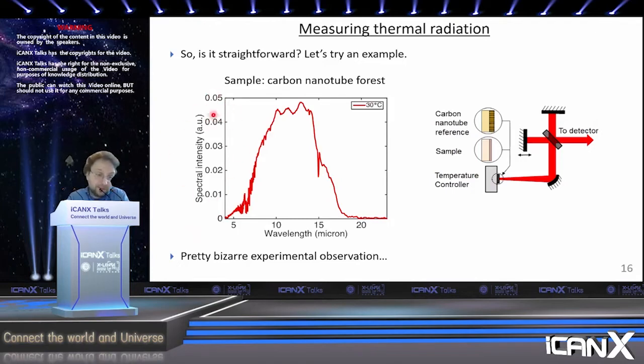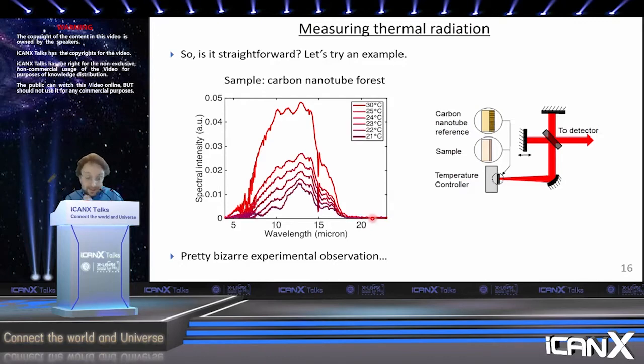I'm plotting the spectral intensity in arbitrary units, because here we're not comparing to any reference. And so the spectrum also includes things like the detector responsivity. So there's almost nothing beyond 17 microns, but that's just because our detector doesn't work out at 17 microns. And so here is the spectral intensity versus wavelength for a sample at 30 degrees Celsius. If you decrease the temperature, your spectral intensity goes down, which is what you expect, right? Hotter objects emit more light, colder objects emit less light, so this is totally normal. You keep going down in temperature, 24 degrees, 23 degrees, 22 degrees, 21 degrees Celsius, everything is totally normal and fine.